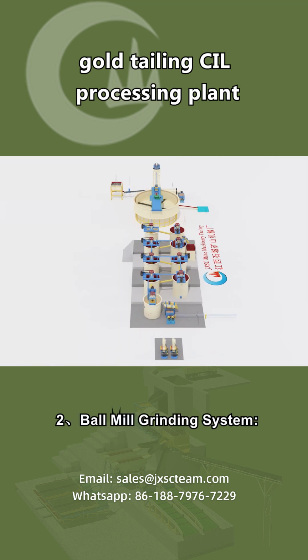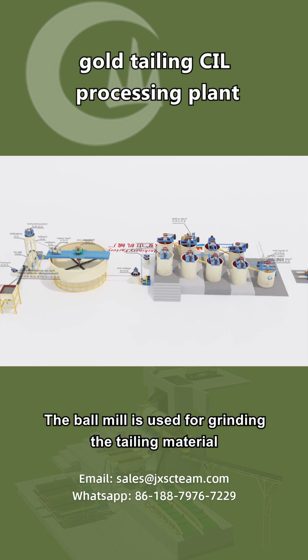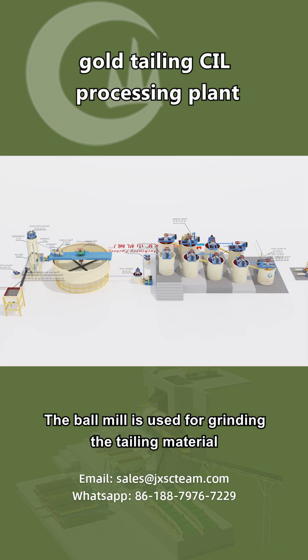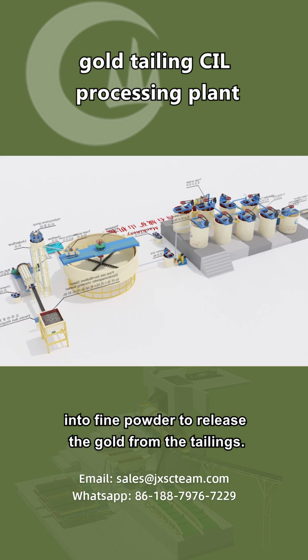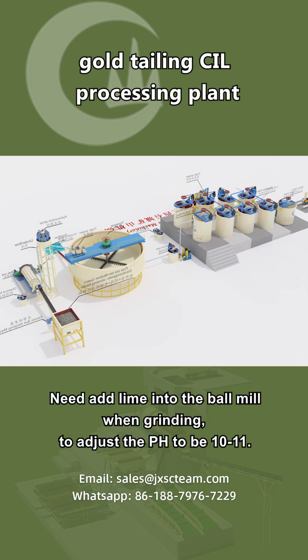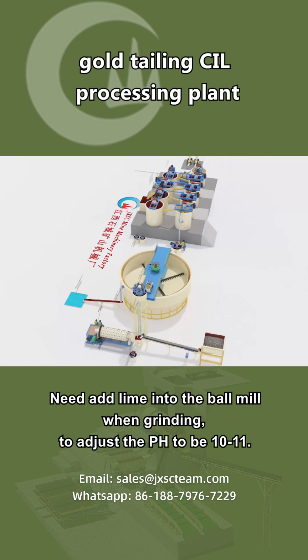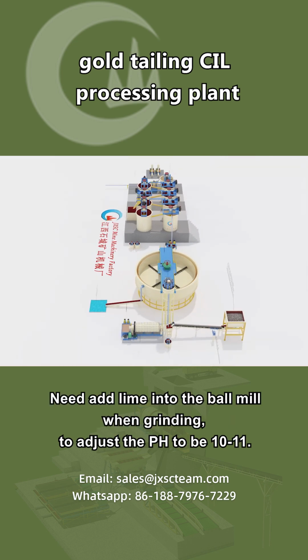2. Ball mill grinding system. The ball mill is used for grinding the tailing material into fine powder to release the gold from the tailings. Need to add lime into the ball mill when grinding, to adjust the pH to be 10 to 11.